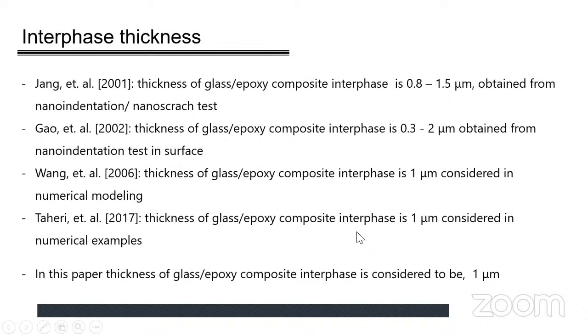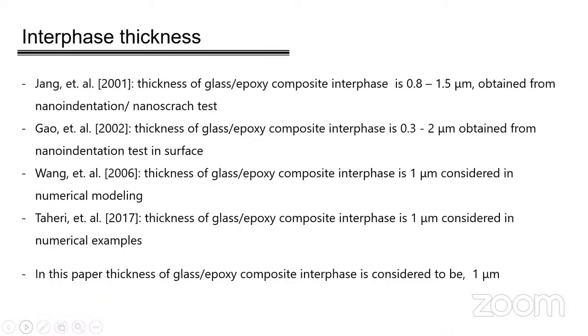One important parameter in interphase is the thickness of interphase. Usually, nano-indentation, nano-scratch tests are used to measure this thickness. And Jang and Gao, for example, calculated that to be between 0.8 to 1.5 micrometer and 0.3 to 2 micrometer. Also, other people used the interphase thickness of 1 micrometer.